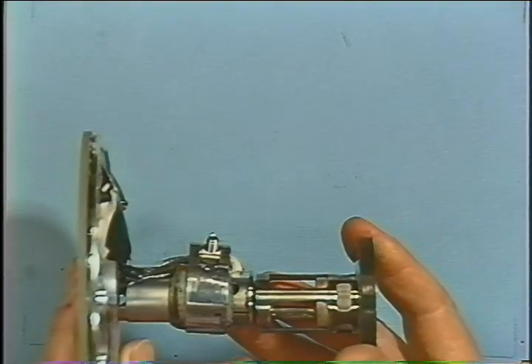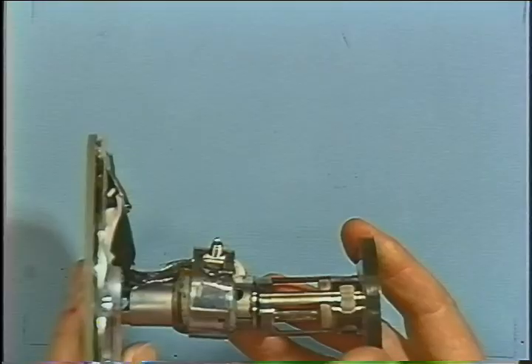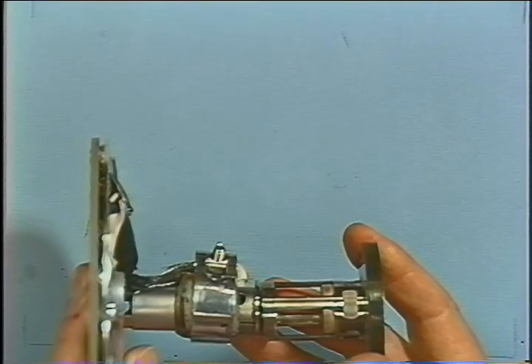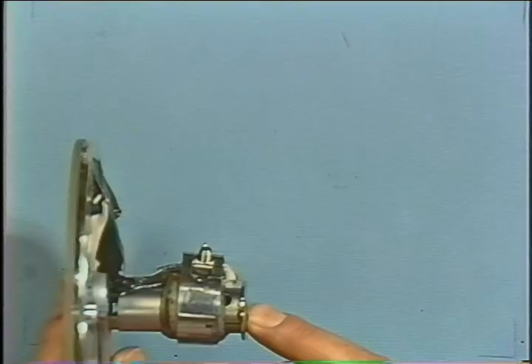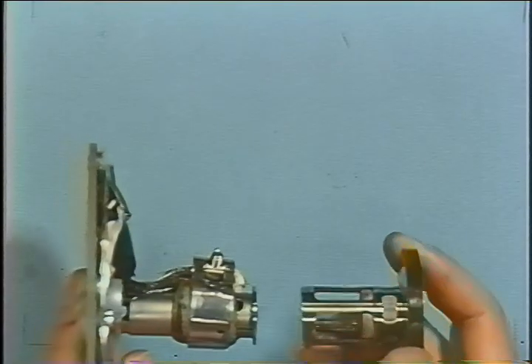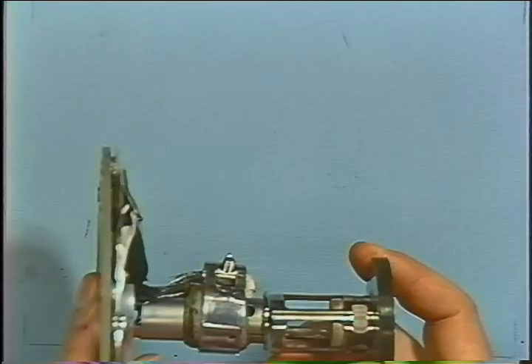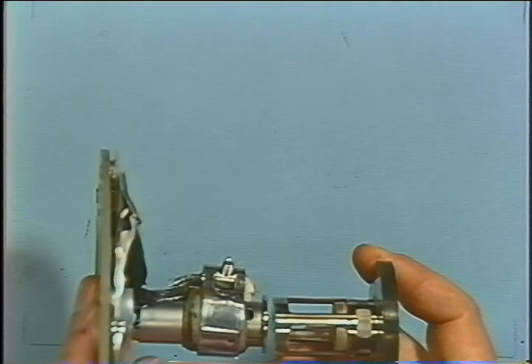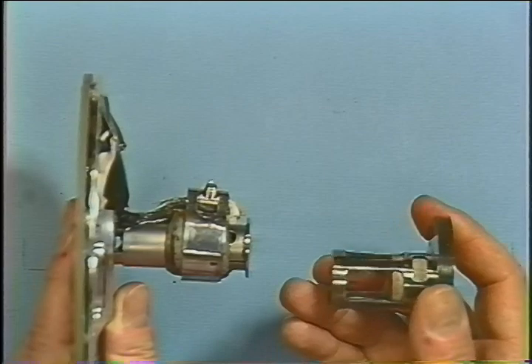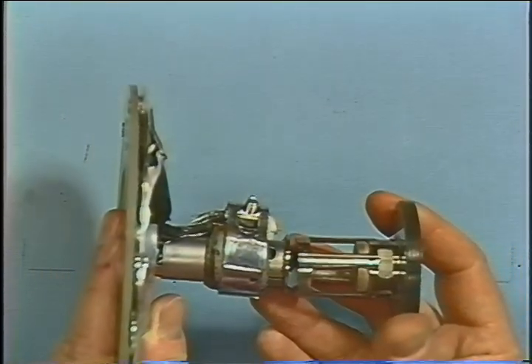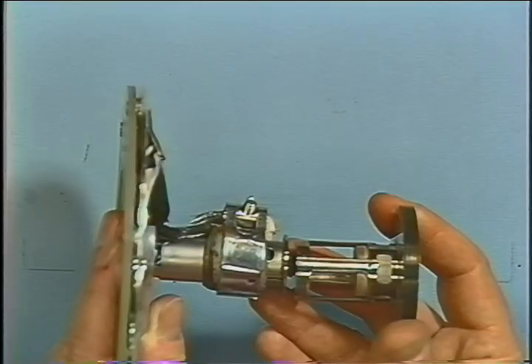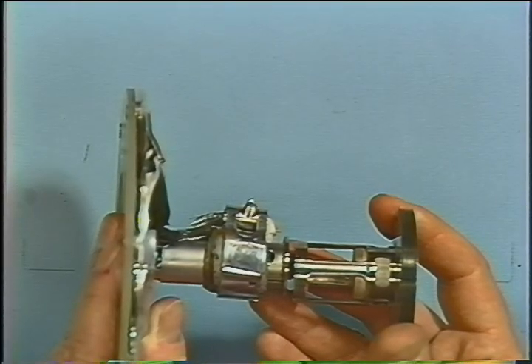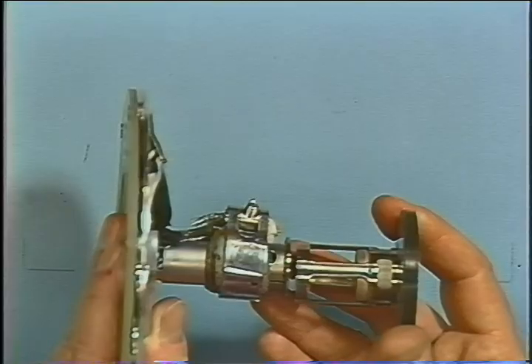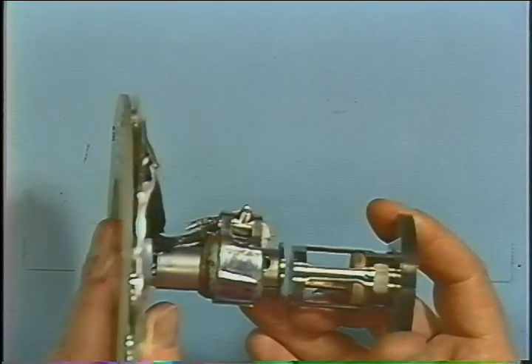Now the plate is touching, or it's very close to touching. The tip of that cone is taken away. So in a real experiment, you put this into contact, and then you separate it as much as is needed so that the virtual tip of this cone is just forming the perfect cone and plate geometry of that system. Note that your spacing is really fixed by that geometry. If your sample would shrink or expand due to volume changes, say with temperature or due to chemical reaction, you could not adjust the gap setting.